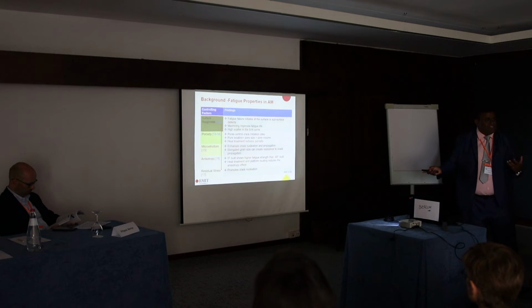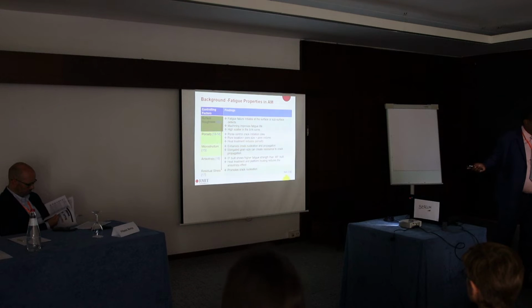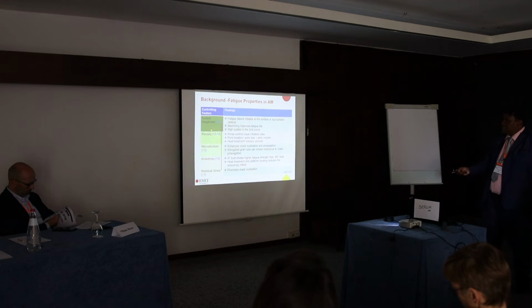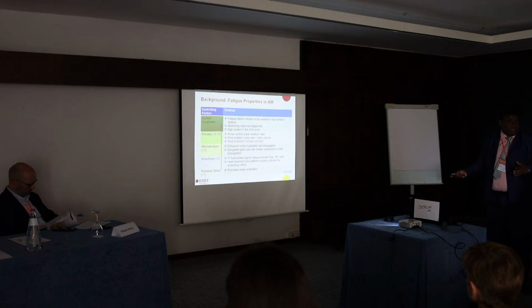Because fatigue is controlled by cracks, and cracks are controlled by the mechanics of fracture. So we are trying to understand everything from the bottom level of fracture mechanics. Looking at controlling factors, surface roughness affects most, and then the porosity, then microstructure, then anisotropy, and then residual stress. Other people have observed that as well.